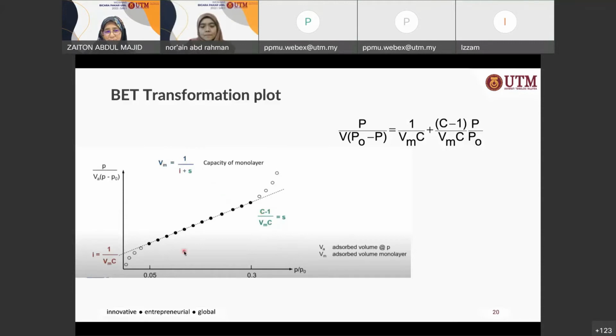Notice that the BET transformation plot only takes the range between 0.05 and 0.3 of P over P naught. Even though you run the isotherm up to a relative pressure P over P naught of about 1 or 0.99 and so on, when you do the BET transformation plot, you only take data in the range of 0.05 to 0.3. This is the classical BET range. But sometimes you need to push it a bit lower, depending on your sample.